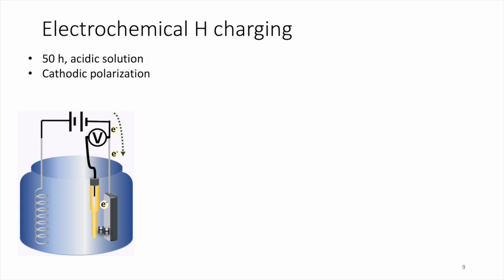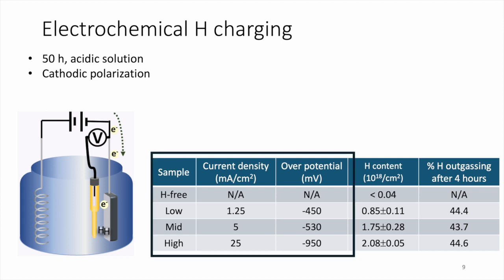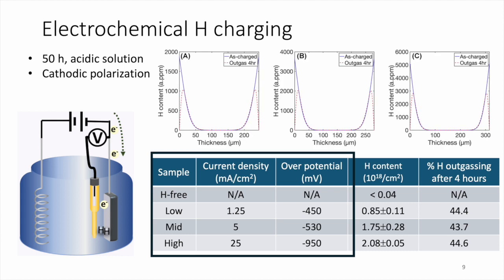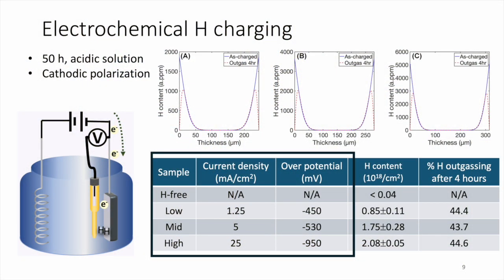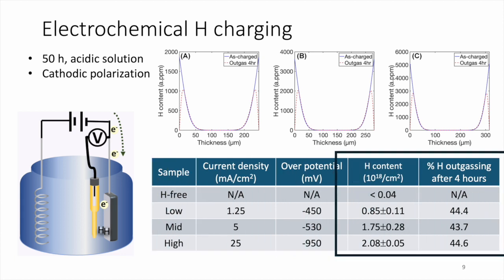The first one is just like the cathodic protection. We put our sample at the cathodic side of this electrochemical cell and charge it at three different conditions. We alter the current density, but we keep the time the same. So with different current density, now we can introduce different amounts of hydrogen. We burn the sample. So when you burn the sample, the hydrogen inside will turn into water. We measure the water, and then we get the hydrogen content of each sample. So if we compare that, it goes from hydrogen-free to low, medium, and high.